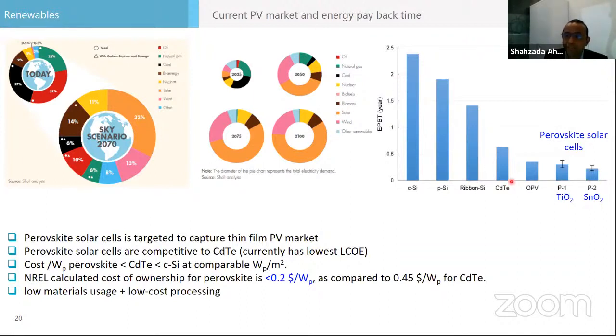And then ribbon silicon, cadmium telluride, OPV, and perovskite solar cells are even lower, because you don't need an energy intensive process. You can heat them at only 100 degrees centigrade, and the perovskite precursor can convert into perovskite material. So titanium dioxide, you need to heat at 400 degrees to convert from anatase to rutile. But if you take another type of oxide like tin oxide or zinc oxide, you just heat them at 100 degrees centigrade. So it is not an energy intensive process, and the energy payback time is very low.